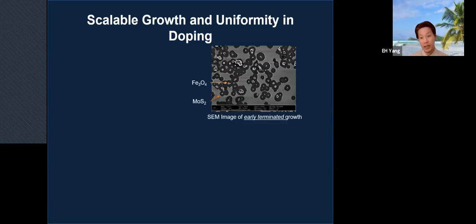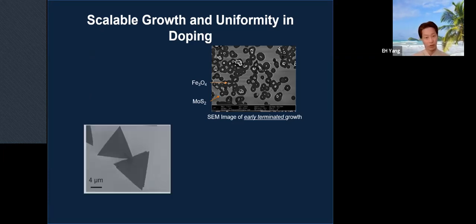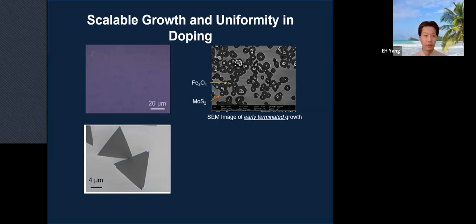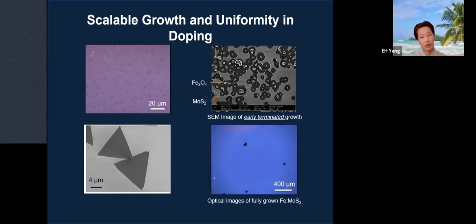So this SEM image shows an early terminated growth to show not fully vaporized iron oxide here. So you see this iron oxide seed with the molybdenum disulfide grains here. And further growth will make isolated single crystal monolayers like this. And further growth will make a continuous film with bilayer spots there. And with controlled conditions, you can remove some of these bilayers. So you have larger monolayer continuous growth with iron doping.